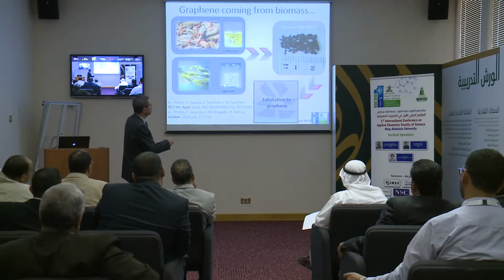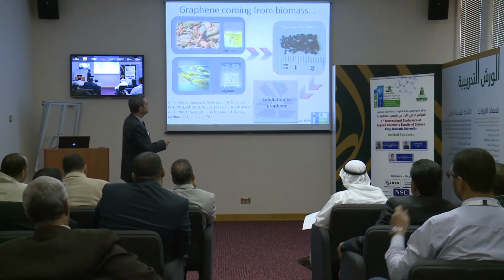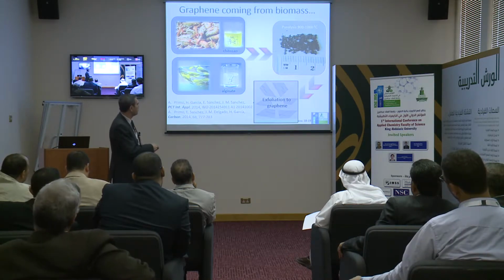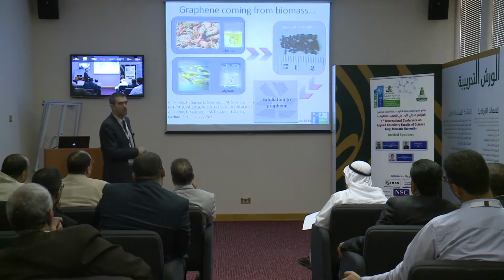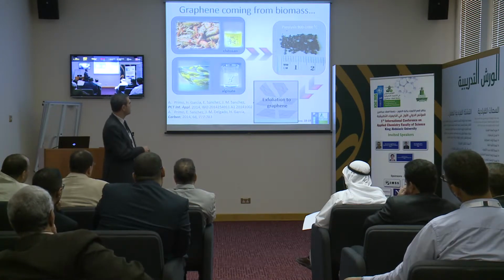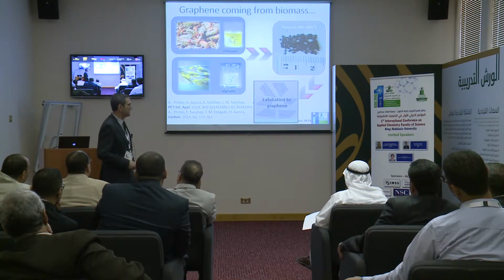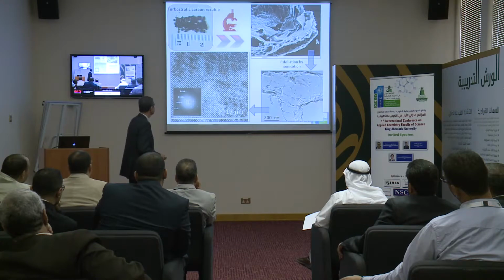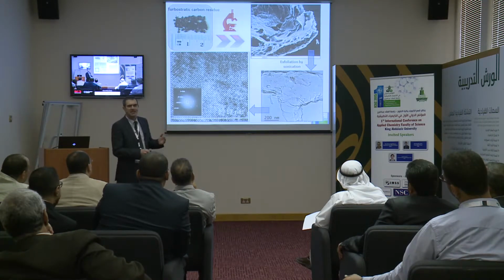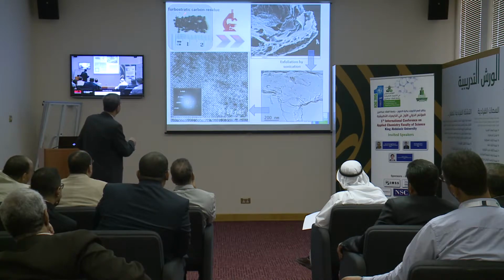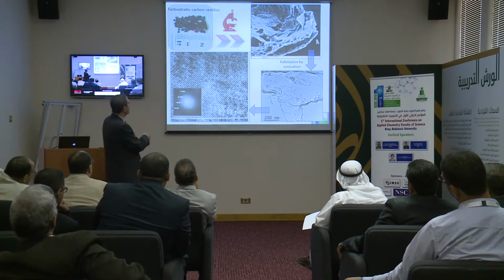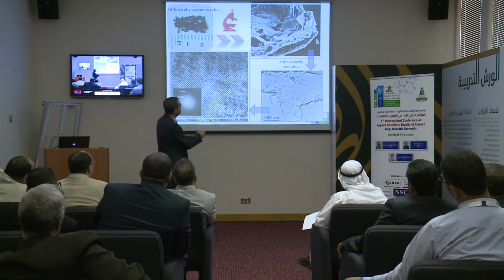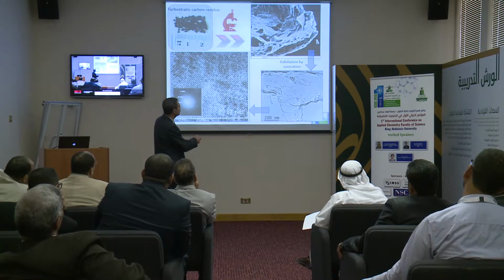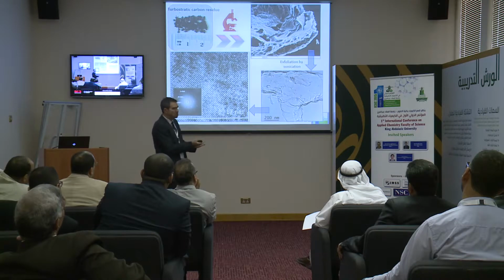We have this carbon here, you can see that the size is very large, and then the interest is that, in contrast to graphite, in which exfoliation is not possible, this carbon is really special, really different, so by sonication we can exfoliate and obtain graphene in suspension in a liquid phase. So here are different magnifications of the carbon that we are preparing. This is the carbon, and it has a name, turbostratic carbon. Turbostratic is because we have layers, and if we expand this image, what we see is that we are forming some layers that at the end will be graphite. For instance, here one layer, another layer. When you consider just the external surface, it is clearly something that is flat.